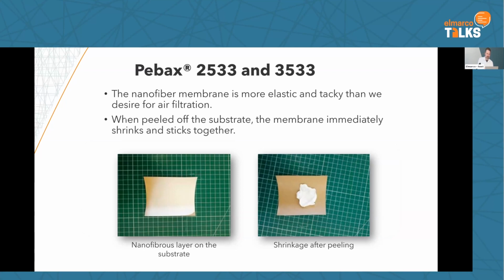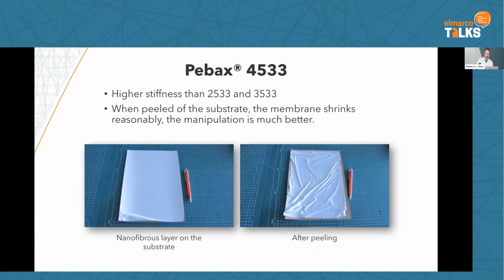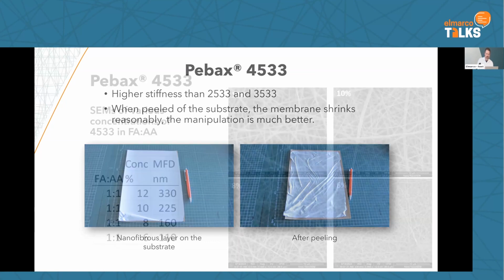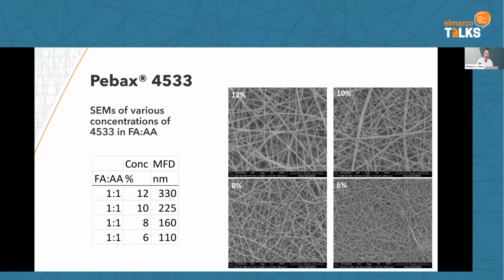But in our application, we want to have a membrane that doesn't shrink so much and have so much tackiness for this particular air filtration application. So the 4533 also spun quite well in our process, and we were able to make nice membranes from them. The other nice thing about the Pebax is that you can get good spinning from quite a wide range of concentration. So we looked at concentrations of Pebax down from 6% all the way to 12%. We can probably go lower and higher even.